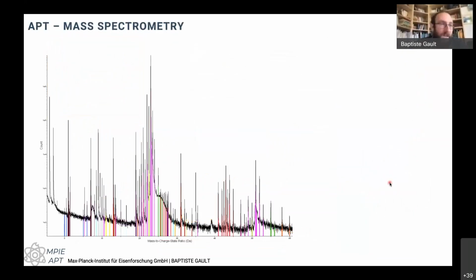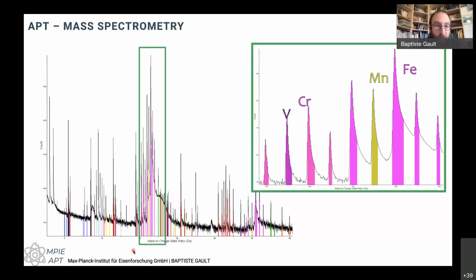So as I said, atom probe is first a mass spectrometry technique. The first thing we get from an atom probe experiment is something that would look more or less like that, a mass spectrum. So we have a histogram of how many ions of a specific mass to charge ratio that we've detected. So we can go down, if I zoom in, we have isotopic resolution.